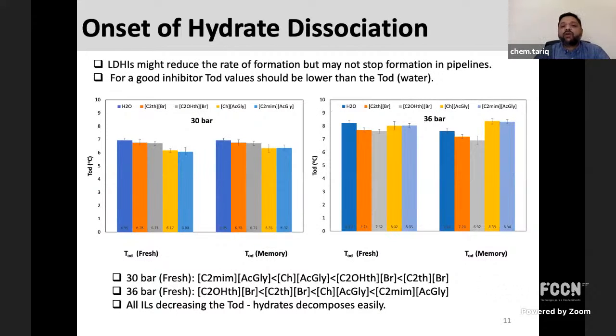Then we did the onset of hydrate dissociation. Many LDHIs can reduce the rate, but they cannot stop the formation of hydrates in the pipelines. So for a good inhibitor, TOD values should be lower than the TOD of water, the onset of dissociation of water. What we saw is that in all cases, even in fresh or in memory, all of them are showing lower values than the water. So that means all ionic liquids are decreasing the TOD, and that means the hydrates decompose easily in presence of these ionic liquids.